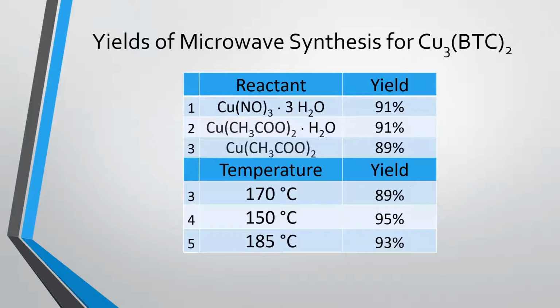When we were able to observe the yields of our microwave synthesis, we found that all of our syntheses had relatively high yields. The reactants had very little change between all 3 of them, even after the water of hydration was removed. The temperature yields were slightly different, with 170 being slightly less favorable than 150 or 185. However, since all of these yields were so close to one another, it's very difficult to make a determination just off of our yields.